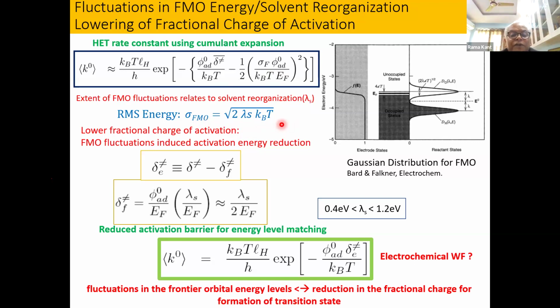Okay, so if I compare with ignoring my fractional charge, the solvent reorganization component, if I include it, subtracts out from that value where it was not included. And this delta F dagger is represented in terms of the ratio of the work function of my adsorbed state and the Fermi energy level. It is scaling, and the solvent reorganization is also scaling with respect to Fermi energy. And the typical variation of this solvent reorganization energy is 0.4 electron volt to 1.2 electron volt.